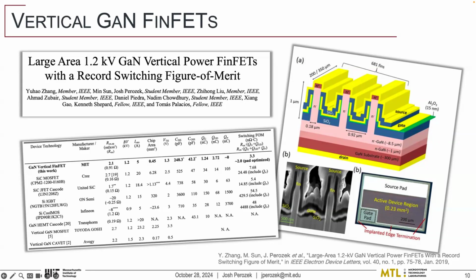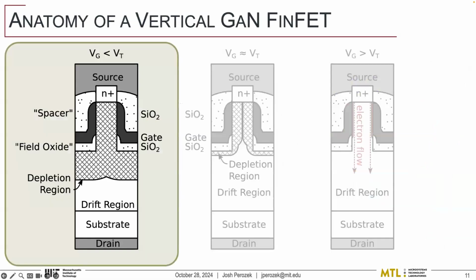So with that motivation, I'll talk a little bit about how they actually work. There we go. The structure of these devices is actually somewhat straightforward. If you start from the backside, you've got your drain contact, and on the top you have a very narrow fin, think 100 to 500 nanometers wide, a micron tall, and on top of that you have your source metal. Normally you would have electrons flow from the source to the drain through that fin, but on the sidewall of the fin we've added a gate structure with the gate oxide. If we put a negative bias on that gate, we're able to fully deplete the fin, and when there's no carriers within the fin, that current doesn't flow. We're in the off state, our transistor's off.